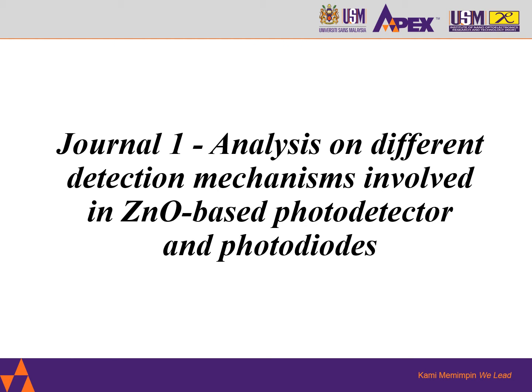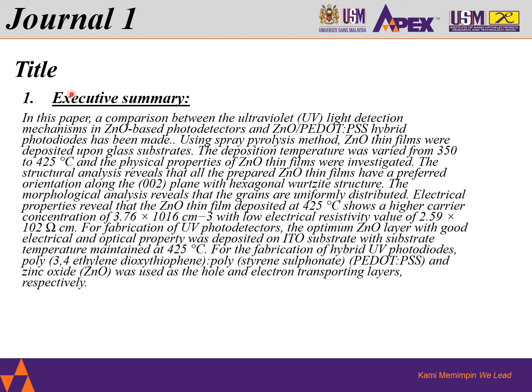Now, the first journal is analysis on different detection mechanisms involved in zinc oxide based photodetectors and photodiodes. The executive summary of the paper: a comparison between the ultraviolet light detection mechanism in zinc oxide based photodetectors and zinc oxide PEDOT:PSS hybrid photodiodes has been made. Using the spray pyrolysis method, zinc oxide thin films were deposited upon glass substrates. The deposition temperature was varied from 350 to 425 degrees Celsius, and the physical properties of the zinc oxide thin